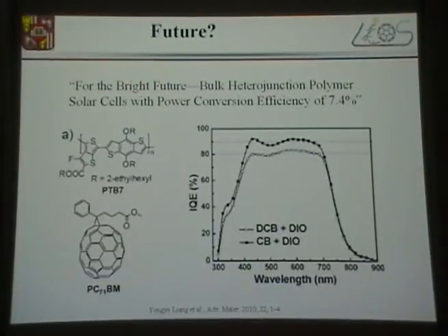And to leave you with the future, 7.5 and 7.4 percent and more high-efficiency solar cells have already been demonstrated. The interesting thing here, as you see, is that the IQE is roofing almost through the entire spectrum. What it actually means is that the losses are around 10%. The losses due to recombination are extremely small. So all of the light that can be absorbed is utilized for the photovoltaic conversion. And you see, this is the 800 nanometer edge, which must be much better than P3HT:PCBM.